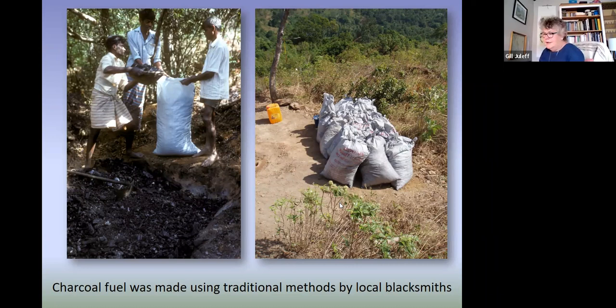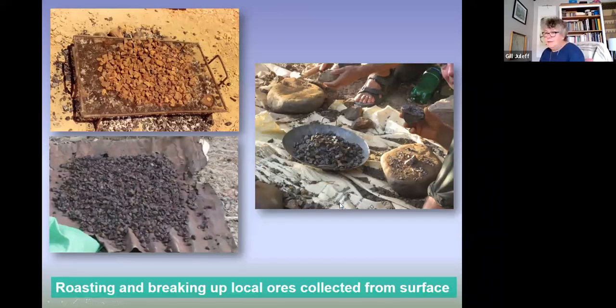We collected iron ore from local sources. They're all surface deposits. It's a really good lateritic iron oxide, mixed iron oxide, which is very good for smelting because it has a good iron content, over 60% iron content, but plenty of other minerals which help in creating the slag and helping to convert the iron oxide to iron metal. So it's a very smeltable ore, and we find this ore all the way across the southern half of Sri Lanka, and it's not something that has to be deep mined for, because it's a weathering product on the